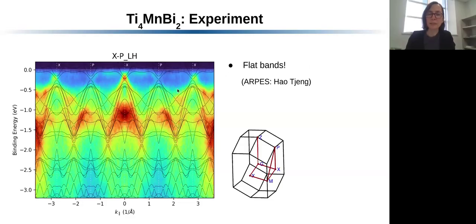Those flat bands were seen in this experiment, for example. This is an experiment called angle-resolved photoemission spectroscopy that allows you to measure the k dependence of the electron's energy. Now, the color map that you see is the result of the measurement. And I have here, close to the Fermi level, a feature that might be a flat band. Now, the lines that you see are calculations, which actually agree quite well with the measurements. And indeed, this feature is a flat band that we have very close to the Fermi level.